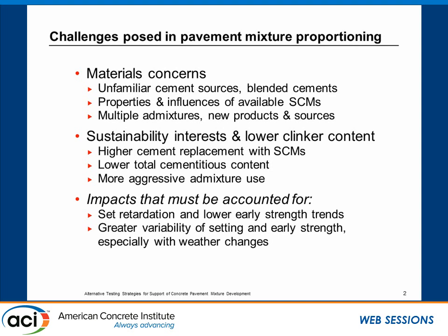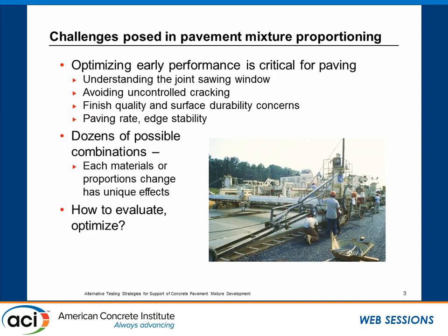We're trying to minimize set retardation, speed up the sluggish strength gain that we might experience from some of these influences, and understand what may now be greater variability of performance as influenced by weather changes. Optimizing this performance is critical for pavements. And the important thing — one that escapes some users — is that every time you change one material in a concrete mixture, you change the behavior of the mix, potentially more than you imagine. The time to know that is on the front end rather than after you've gone into a project.